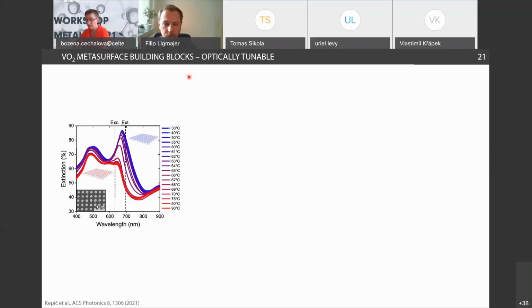So similarly to the previous work with UV light, here we took an array of nanodisks, and here you can see its extinction. So here you can see this characteristic behavior, how you go in the visible range from one sort of dielectric Mie resonance into another form of dielectric resonance, and we excited our nanodisks with a visible light laser. So by a red laser, we illuminated our sample, and we measured extinction at a higher wavelength. So we looked at the region where the change is supposed to be highest, and influenced it by visible light. So we were able, by visible light, to tune the visible red transmission through our material.